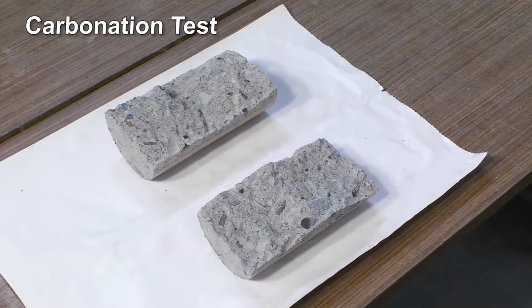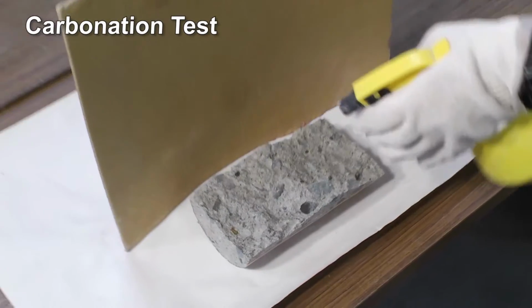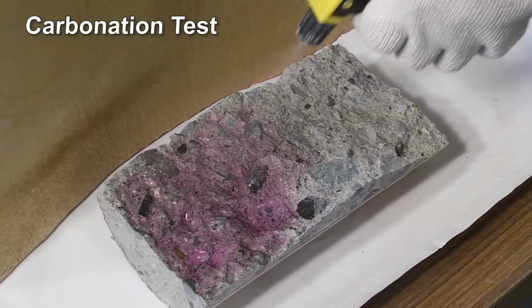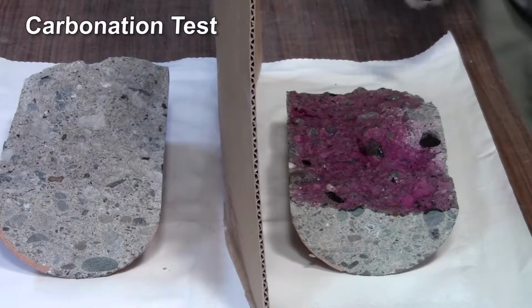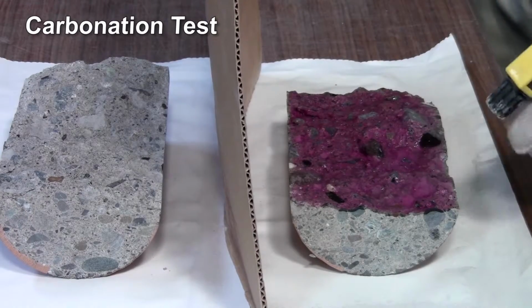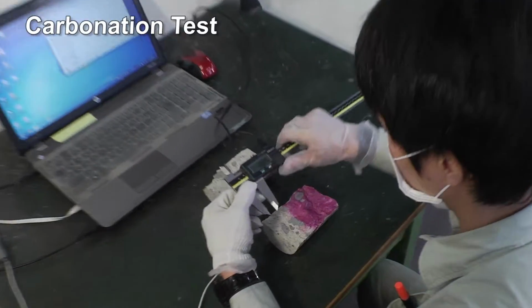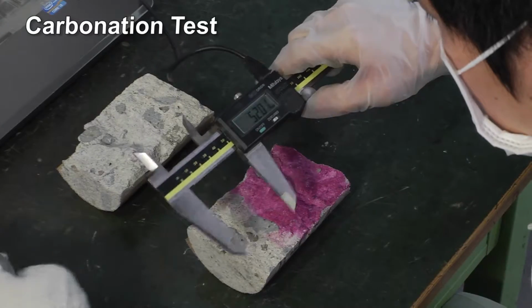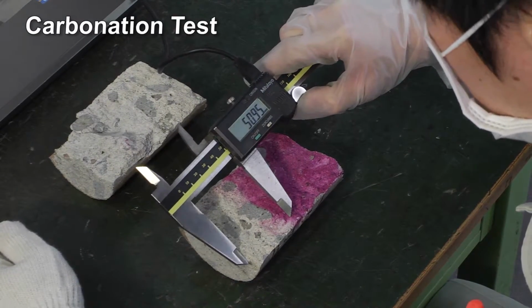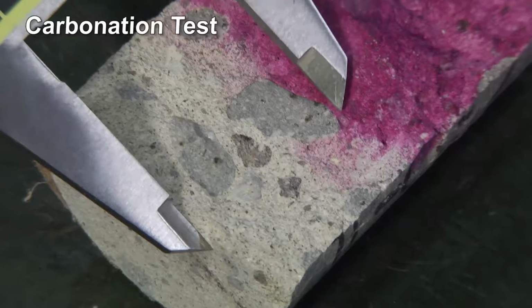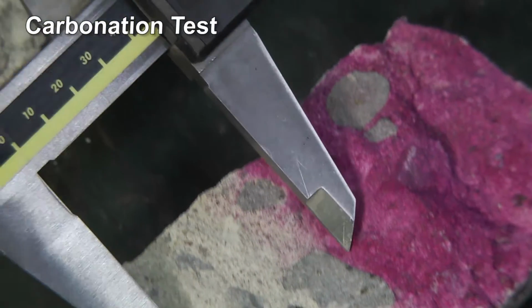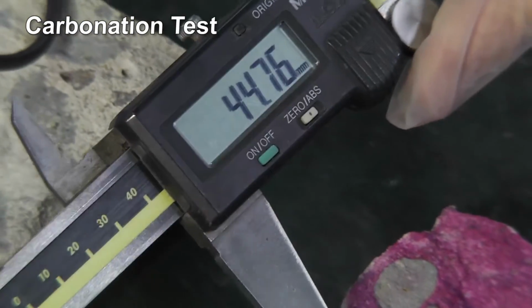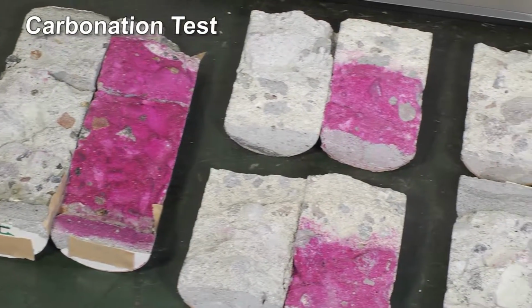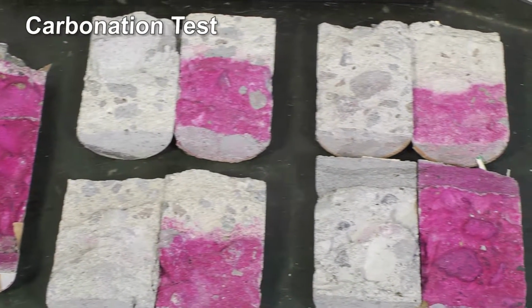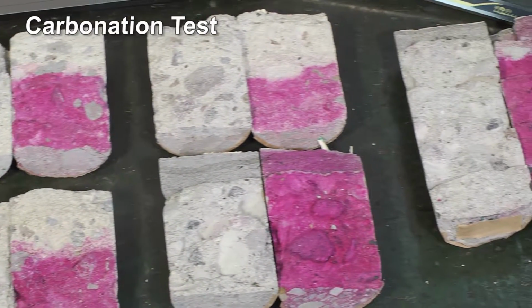In the carbonation test, the test specimen is first split in half and just one side is sprayed with a phenolphthalein solution. The non-carbonated section shows a purplish red, while the carbonated section shows no coloration. The distance from the surface of the test specimen to the carbonated section is measured, and this data is used to estimate the deterioration level of the concrete.